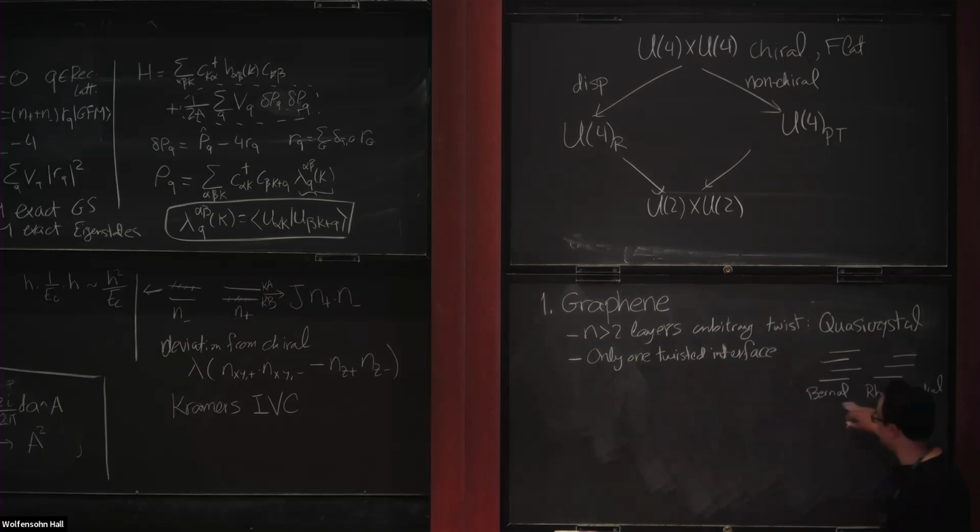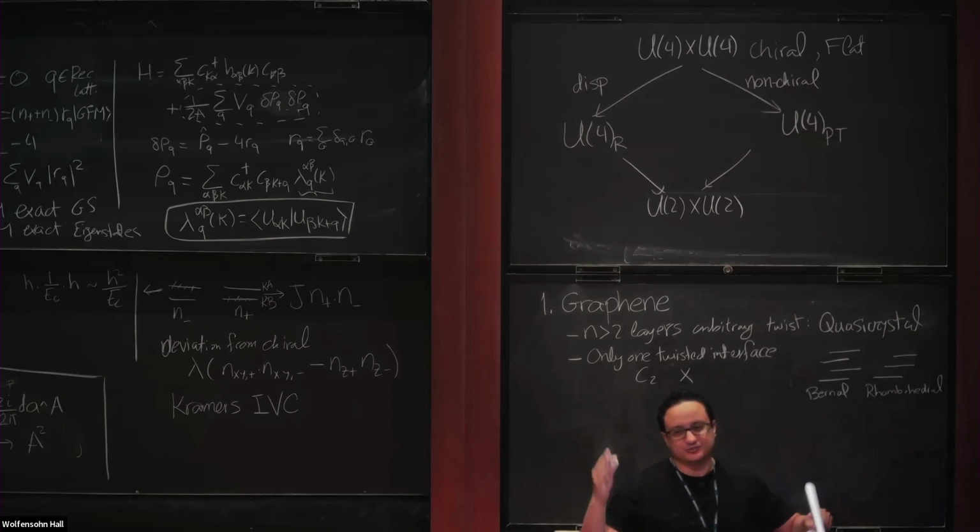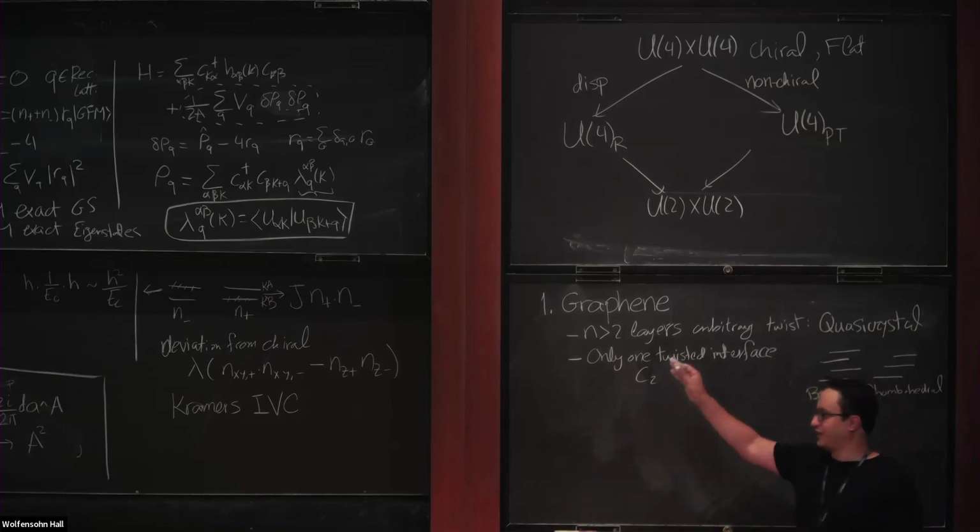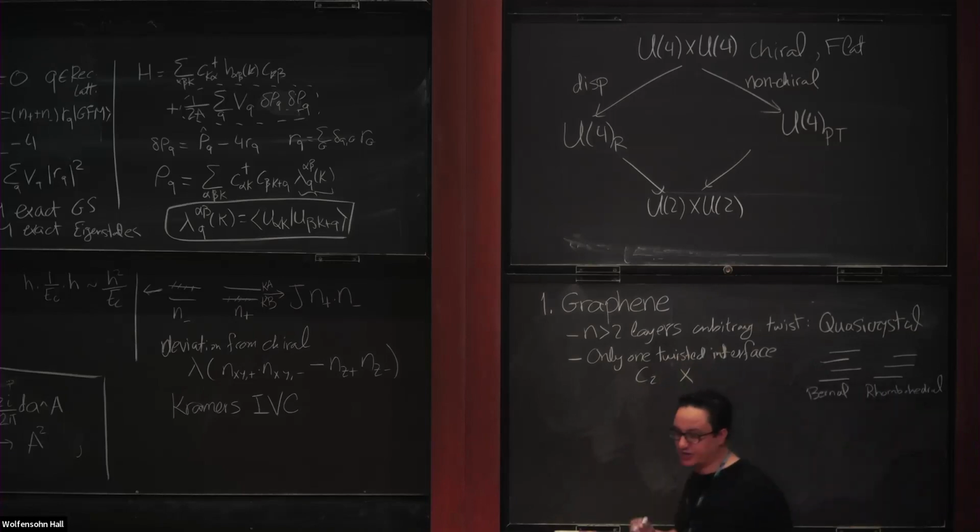Now, both of these configurations break C2. So all multi-layer graphene systems based on a single twist angle and having a Bernal or a rhombohedral subsystem, they break C2. And also, they turn out to either be not superconducting or be very weakly superconducting, not as robust as twisted bilayer graphene, which led to a suggestion that maybe C2 symmetry is somehow important for superconductivity. But also, there could be other differences between these two systems. So this may be the case or may not.